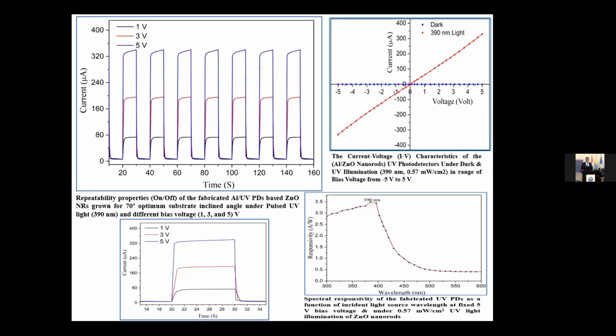The obtained high photocurrent of the UV photodetector device is referred to the high quality crystalline and the high surface area to volume ratio, related also to the high aspect ratio of our sample at the substrate inclined angle, which is 70 degree. Also, at the different bias voltage, from this figure, we can conclude the fabricated UV photodetector has excellent stability and repeatability behavior.